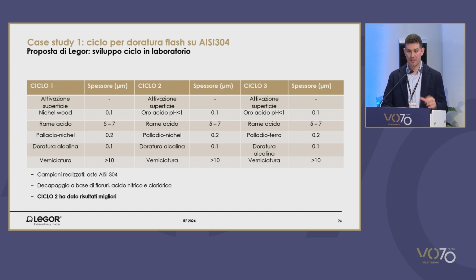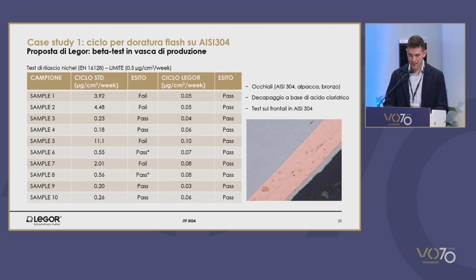Performing the release test, we saw that cycle 2 and 3 were granting best results. This means that nickel wood did contribute to the release of nickel. Cycle number 2 is the one that was tested because it was more similar to the cycle that we resorted to earlier on with palladium nickel.